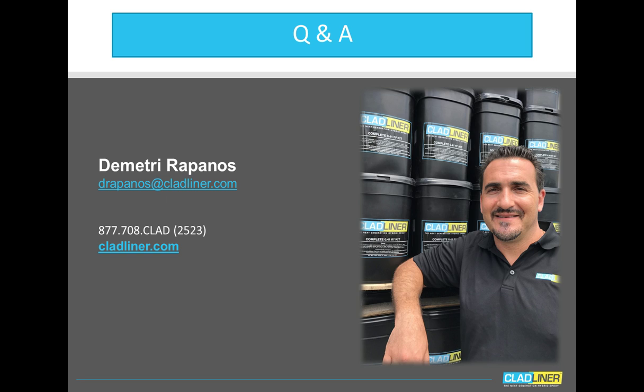How easy is it to apply Cladliner, and what kind of surface prep is required? As far as surface prep goes, we always recommend we want to get back to a clean, sound, contaminant-free, pH-neutral substrate. In our case, with the Cladliner, we want it moist, so that's what we need for prep. Typically, power washing is all that's needed in a manhole. Depending on the conditions, it could be others, but usually it's power washing, so that would be the prep.